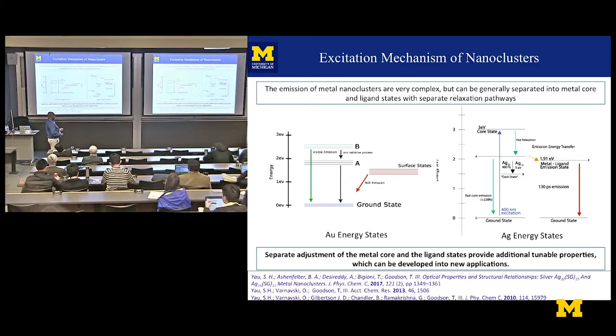Even though the electronic structure, if you count electrons, the Fermi energy levels, all of these things are very similar, for the case of silver it's actually looking different. We were surprised. So actually, you have some excitation to the core state. That's similar. But then there's some fast relaxation to the so-called dark states. And in the case of 32, this dark state only lasted for less than half a picosecond. And in the case of silver 15, it lasted for 5 picoseconds.